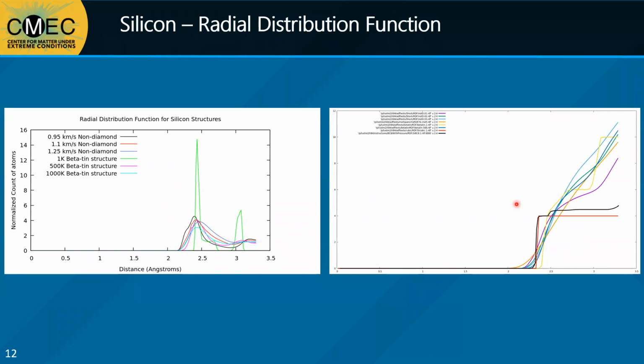On the right, we show the cumulative distribution function for silicon atoms of various phases. There are definitely some marked differences in some of these phases. For example, the simple cubic and the BC8 phases have a very sharp rise at about 2.3 angstroms, compared to the rest, which have a more gradual rise. However, there is still no conclusive match when comparing these against our shocked silicon sample. There is some extra information that we can find from this cumulative distribution function, as the value of the cumulative distribution function at a certain distance can be corresponded to the density of the atoms around a specific atom.